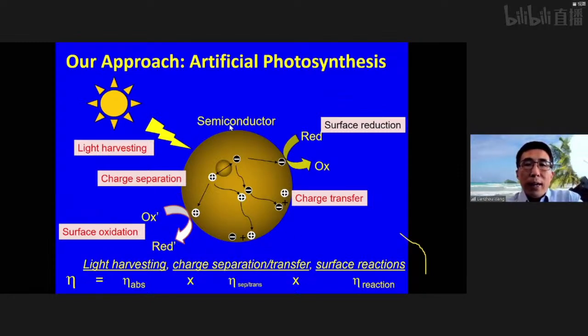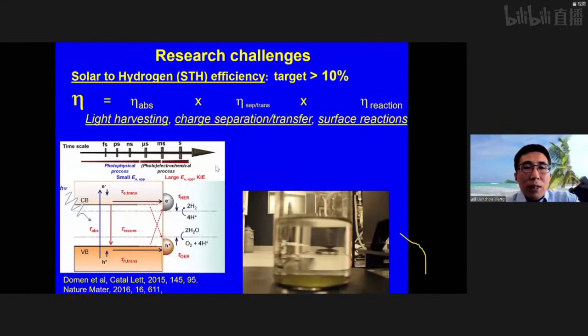And so if we can have good management of these three key steps, like light harvesting, charge separation and transfer, and also the surface reaction, we have good hope to achieve good efficiency. But unfortunately, so far the efficiency is very low, only in single digits. And what we really want is to achieve a solar-to-hydrogen efficiency of at least 10%. Why 10%? That's because the current gas reforming process to produce hydrogen is pretty cheap, and we really need a very good efficiency to be compatible with